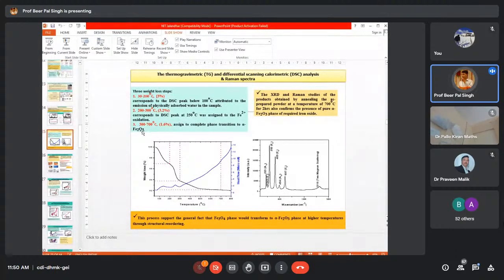And ultimately the third weight loss, much smaller than the first and second ones, was 1.6%, and that occurred between 300 to 700 degrees centigrade. Beyond 700 degrees centigrade, because we sintered it up to 800 degrees centigrade, it was almost constant. So in that case, that really suggests that there is a complete phase transition to the alpha phase of iron oxide